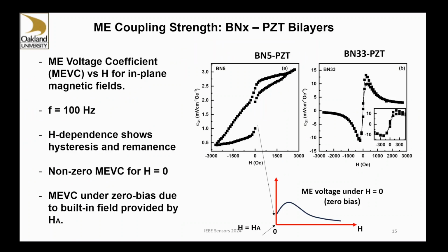These are some of the data. This is the voltage response versus bias field. As you see here, at zero bias, there is significant voltage response. So it is the effect of self-biasing for the ferromagnetic phase. And these are data for increasing amounts of nickel ferrite. So with increasing nickel ferrite, the overall voltage response increases. And this also has zero field response.